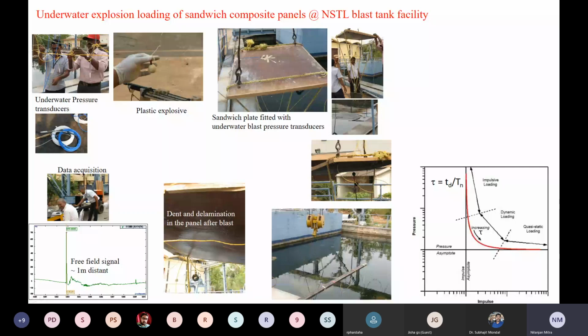As you let it explode, you see what kind of dimples are formed, and then compare that with steel of a similar weight. What we found is that this material performs much better than steel. Steel is, first of all, much heavier, so it is not lightweight, and it cannot carry that many passengers or other equipment, right? So a lightweight material is good for the Navy. That is why this material is utilized by the Navy nowadays for naval applications, at least.